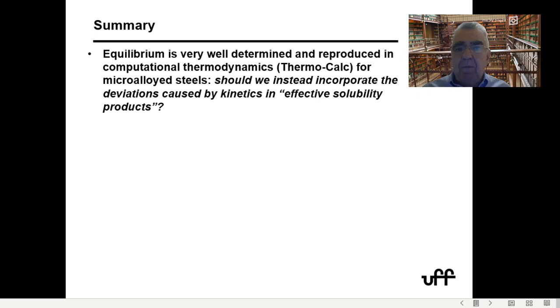And so in summary, to not go too much over the time, I think equilibrium is now very well determined and reproducing using computational thermodynamics. So I think it's very dangerous now that we keep on using effective solubility products, including those that people say, well, this is better because this was determined in industry. Of course, it may be better if you determine for your steel in your plant, but if you're trying to use something that was empirically determined in another condition, it's going to be very difficult to be able to fit, and it's going to be probably not useful for extrapolations and for alloy design.